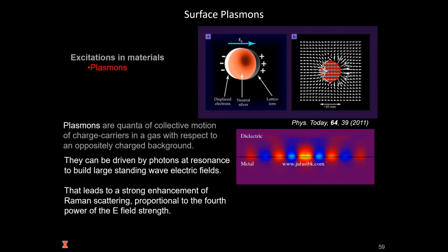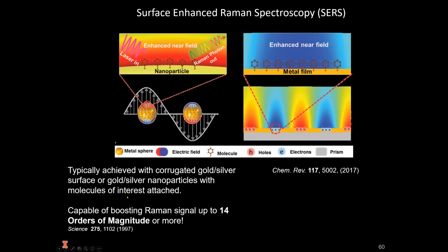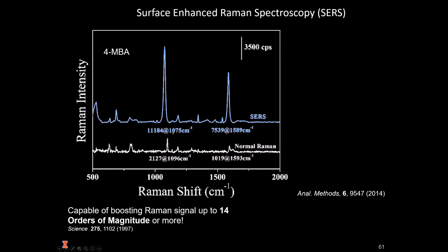Surface enhanced Raman spectroscopy makes use of surface plasmons to do exactly that, and it's capable of boosting the Raman signal up to 14 orders of magnitude, according to some calculations. Here you can see that enhancement, though not 14 orders of magnitude, it's very clear that there is a huge enhancement when you use a SERS substrate versus a normal substrate without the surface plasmons.